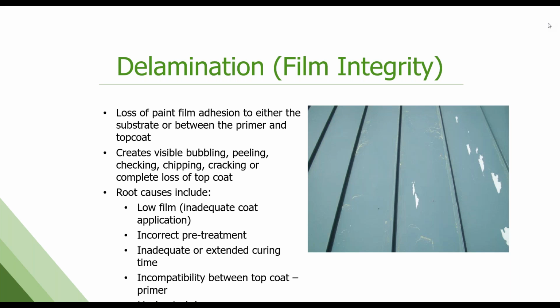It can also be caused by, and this is the most common one we see, but it's hard to prove, mechanical damage during installation. So the panel gets scratched up, they don't correct that or fix it, you now have an opening in the coating that over time, water and moisture and stuff can get in there and starts to lift that paint up. You'll notice on this example on the right, there's some very straight vertical lines where that paint is peeling. We concluded that this was most likely scratching during installation that resulted in this. Next slide.